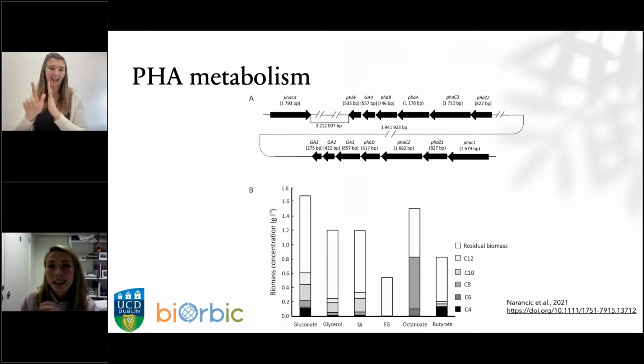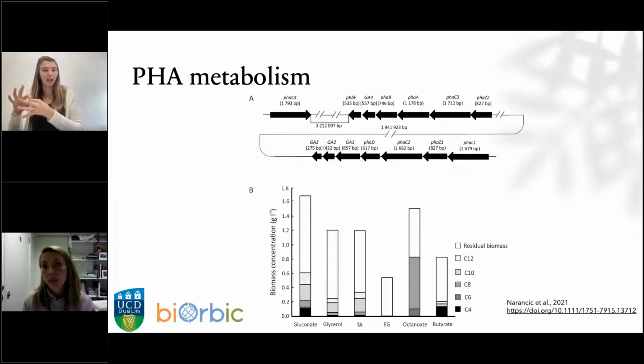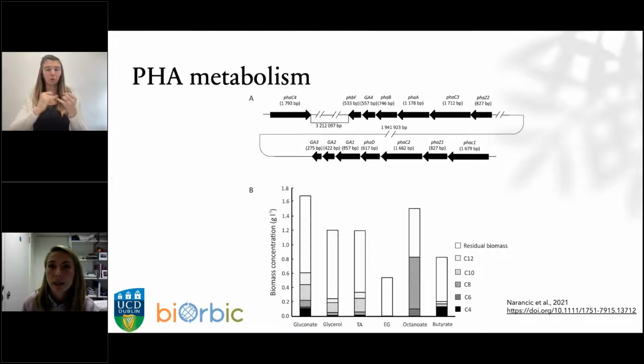Another thing that GO16 is absolutely amazing in is that I have mentioned that you have two classes of PHAs. We have short chain length PHAs, and I mentioned polyhydroxybutyrate as a representative, and then we have medium chain length PHAs that are mainly accumulated by Pseudomonas species. So you would have Pseudomonas species that can accumulate medium chain lengths. A few of them would have the capacity to accumulate polyhydroxybutyrate, but it is very rarely found in nature that a bacterium can accumulate both natively. And our GO16 can do that. So we have also identified the blueprint that allows GO16 to do this.